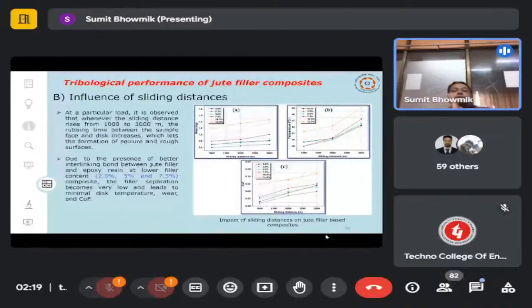Similarly, with the sliding distance, if we consider the distance travelled by the developed component, with the distance the wear is more, the temperature is high and the coefficient of friction is high. But it has been found that 2.5 and 7.5 in most of the cases are giving the minimum disk temperature and coefficient of friction with the 1000 to 3000 sliding distance.